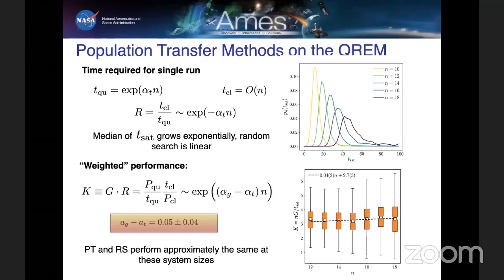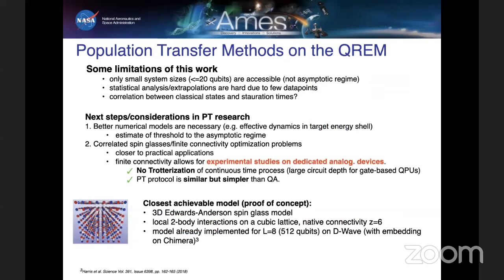We have a weighted performance measure, essentially the probability of success divided by the time, and this is the ratio between the quantum and the classical one. This is a battle of exponents that essentially sums up to 0. So PT and random search at these system sizes perform approximately in the same way. This is maybe disappointing, but I still think that the analytical prediction is correct. So essentially we see this as a finite size correction on top of that.